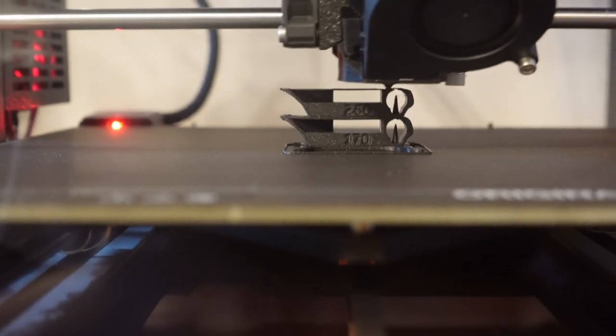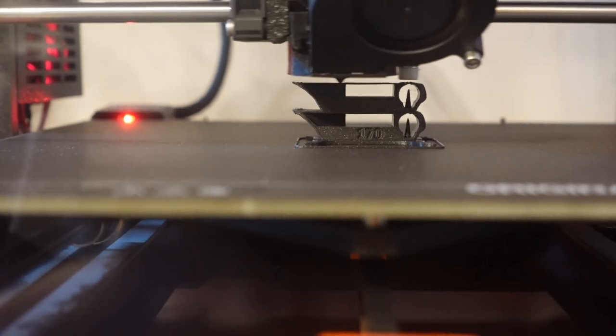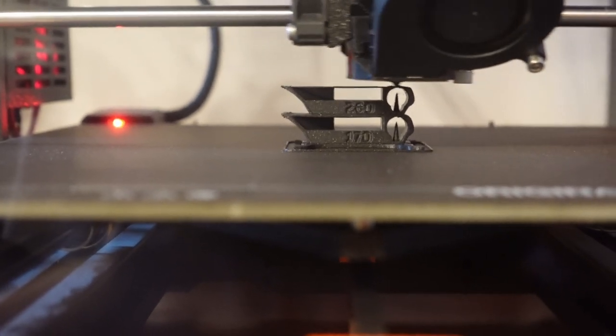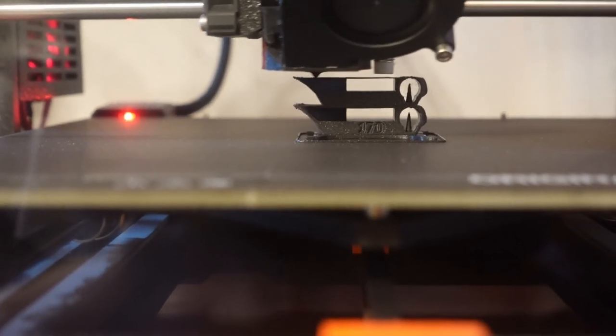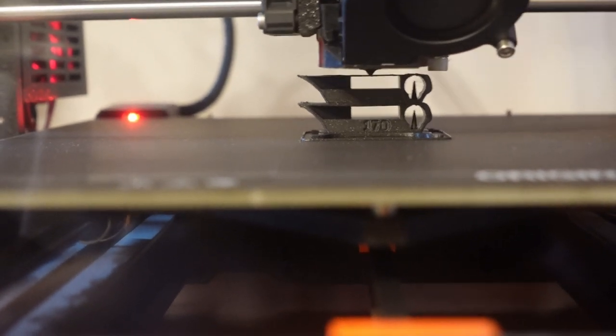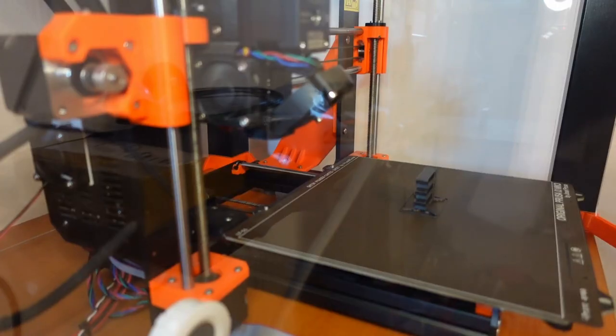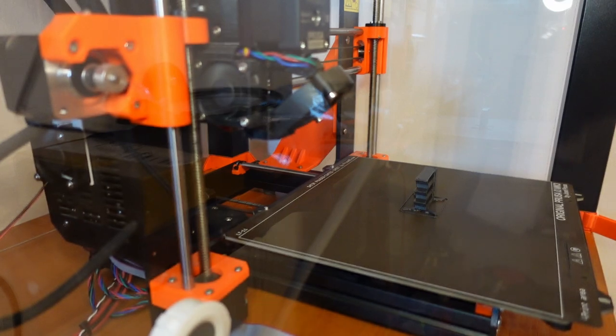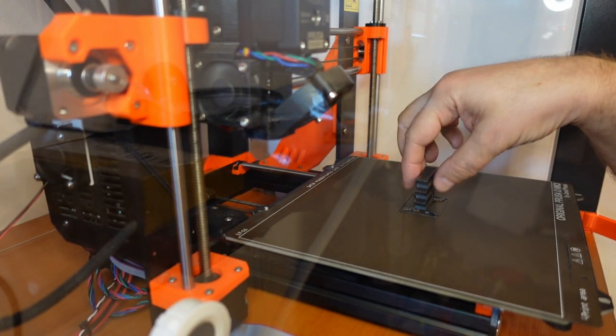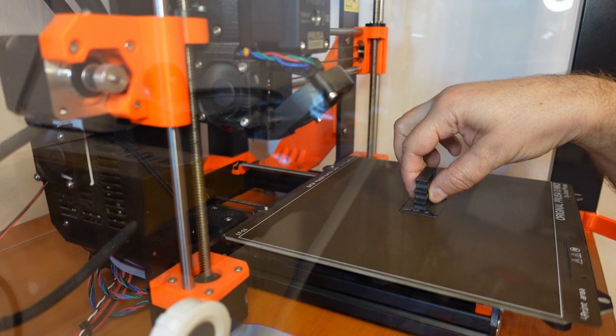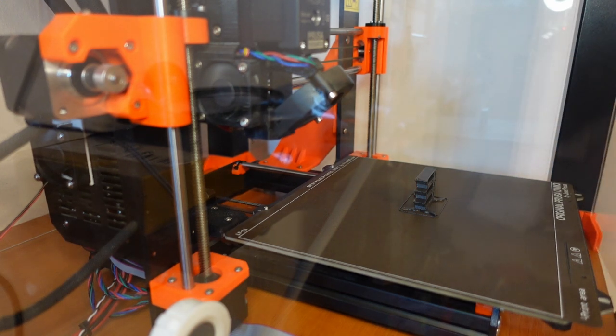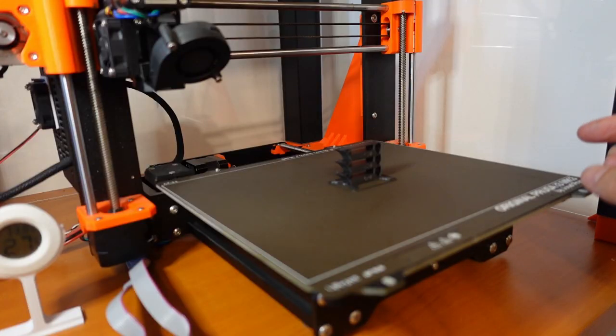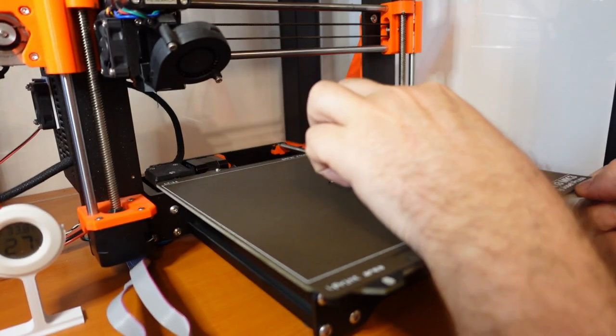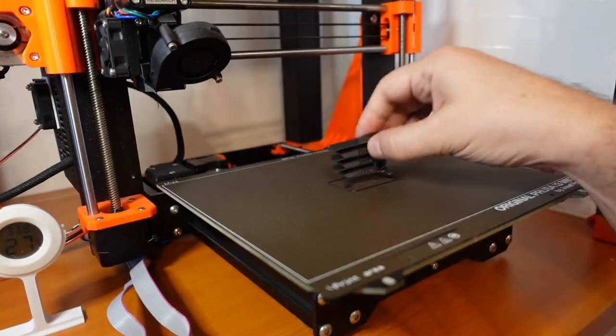I just captured the bridging moment, which is always a problem with ASA and ABS without any cooling. But it looks good. Printing is finished. The temperature went up to 46 degrees Celsius inside, and the bed adhesion is great. I will wait until it cools down, and probably it will be very easy to remove the object. Okay, so the bed cooled down to 40 degrees Celsius, and let's see. Oh, it's completely removed.